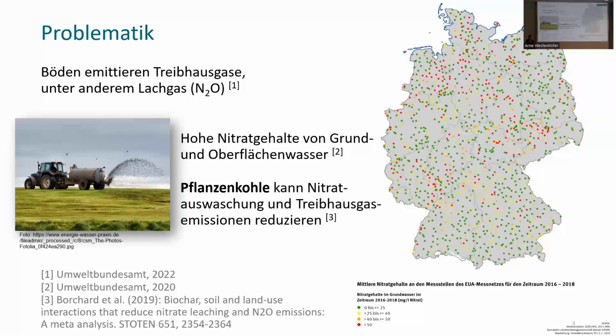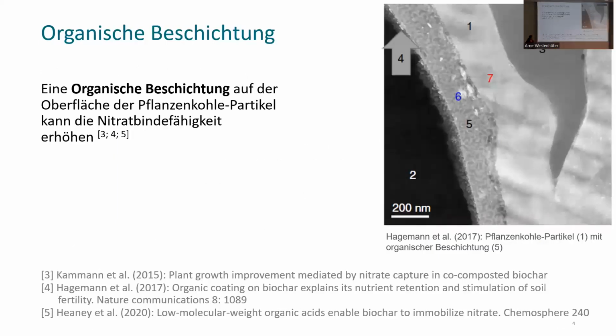And we found out in a couple of studies, not only us, but many other people, we realized that the negative consequences can be reduced by using biochar. It was realized that if you combine biochar with something organic, for instance, this is the picture of Nico Hagemann's group. You see the organic coating on the surface of the biochar plant particles. And this organic coating can improve the properties of the biochar. Other studies have come to the same result, and that is with low molecular acids, this can be related. And this leads to better capacities, better properties.